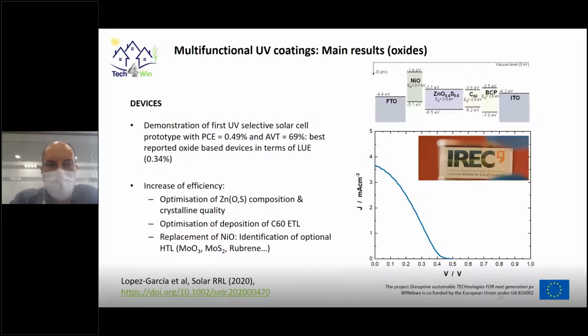As for the optoelectronic characterization of the devices, we have worked with an ultraviolet intensified solar simulator, because one of the problems for this kind of devices is that in standard solar simulators, the ultraviolet spectral region is not well reproduced compared with the spectral region of the solar radiation. So we have been able to demonstrate the first ultraviolet selective solar cell prototypes, which are still non-optimum devices, of course, with a low efficiency of almost 0.5%, but we have a very good transparency, 69%.